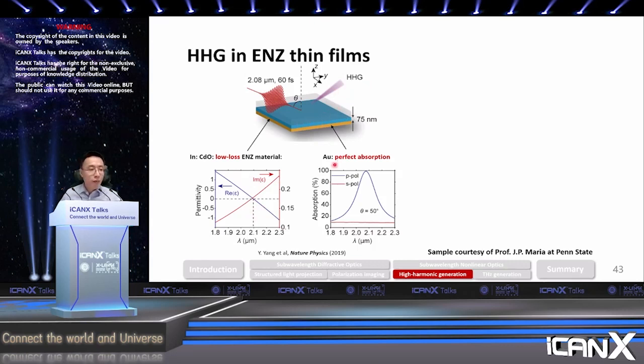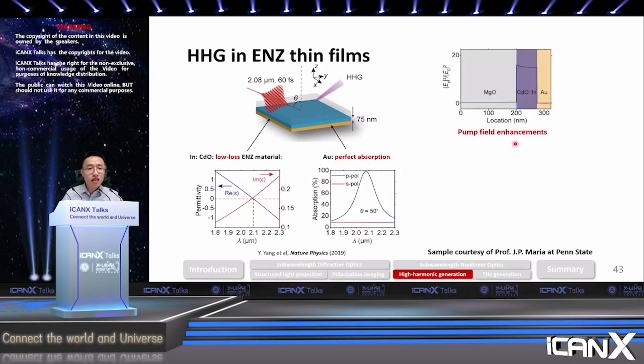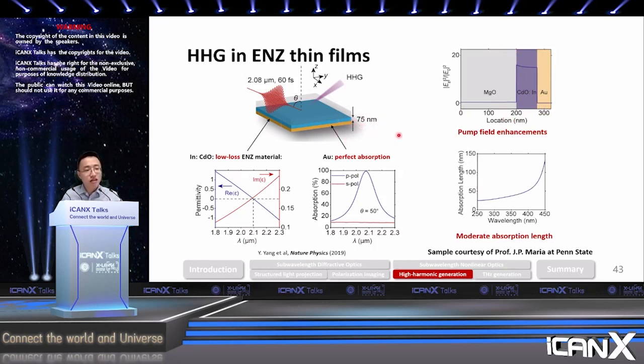Because of this epsilon-near-zero effect, we can expect from the transfer matrix calculation that you indeed get a large field enhancement inside this ENZ layer. Another important thing is that this thin film has a thickness of only 75 nanometers, which is comparable to the absorption length of the material in this UV range. So we can still get quite efficient extraction of the harmonic signal this way.